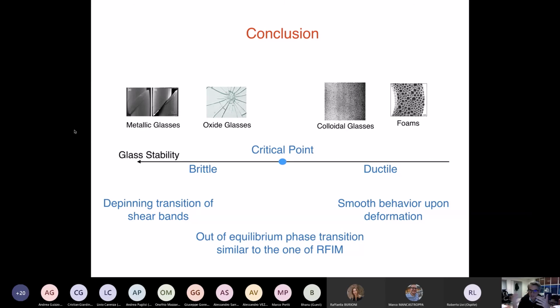But in reality, we can understand and rationalize all these different behaviors by thinking that foams, colloidal glasses, or granular materials are systems with a very low degree of annealing, just because the relaxation times at the microscopic scale, compared to the macroscopic timescale, are very small, and instead metallic glasses are much more annealed. So metallic glasses are more annealed, with low disorder, and so we expect a brittle, discontinuous behavior, and indeed foams and colloidal glasses are high disorder, and so we expect a ductile behavior, and we expect a critical point between the two.